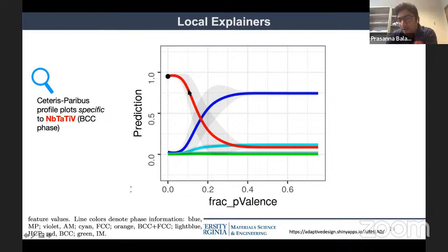But as you increase the p electrons in the composition, this can be achieved, for example, by adding elements like aluminum and so on. What that tells you is that if you add aluminum, the probability of forming the BCC phase decreases and the mixed phase increases, right? So what this is telling us from a conceptual standpoint is that aluminum might react with these transition metals and may precipitate out an intermetallic compound, essentially disrupting the single phase BCC structure and giving us the secondary phases, right? So we are beginning to appreciate and unravel these trends at this particular level so that we can begin to explain what the model has learned about every single data point in our data set and provide an interesting explanation, right?